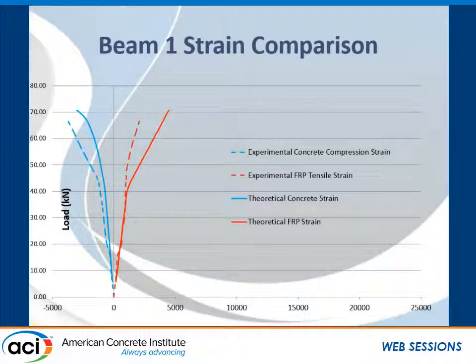Now, the section analysis that was developed to account for slippage effects in predicting ultimate load had to be modified to predict the behavior of the cross-section at loads less than ultimate, as the concrete was not near the crushing strain. We used a concrete stress-strain relationship from Todeschini to develop both the strain relationship and also to develop moment curvature diagrams for the strengthened cross-sections over this entire spectrum of possible values of concrete strain.